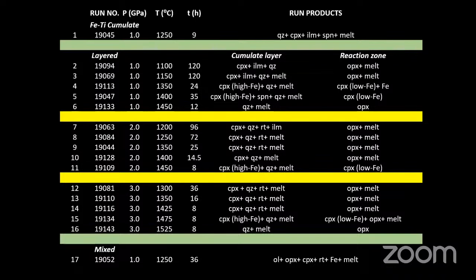So our results are summarized in this table. We have conducted about 15 layered experiments, at pressures ranging from 1 to 3 GPa, like at 1 GPa, 2 GPa, and 3 GPa. And we have got different phase relations as we have increased the temperatures at each pressure.